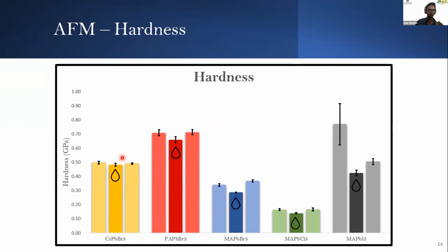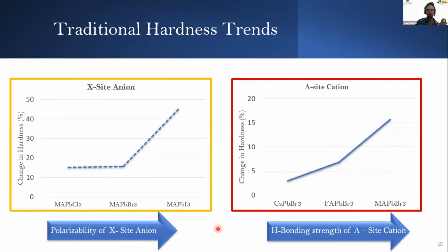So we think that this is due to material degradation. Again, the cesium lead bromide, the completely inorganic halide perovskite crystal, didn't experience significant change in its hardness when we changed the humidity. Taking a look at the trends from the hardness measurements, we find the following correlations. There is a weak correlation between the polarizability of the X-site anion and the change in hardness that the crystal experiences, and a stronger correlation between the hydrogen bonding strength of the A-site cation and the extent to which the hardness of these materials changes.